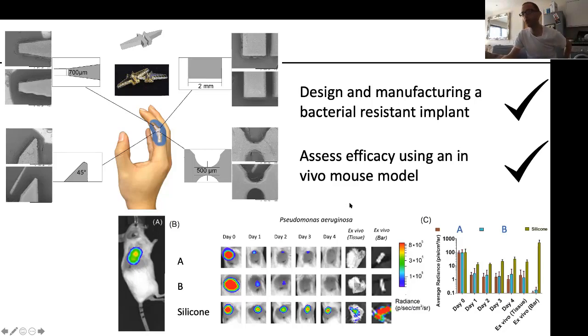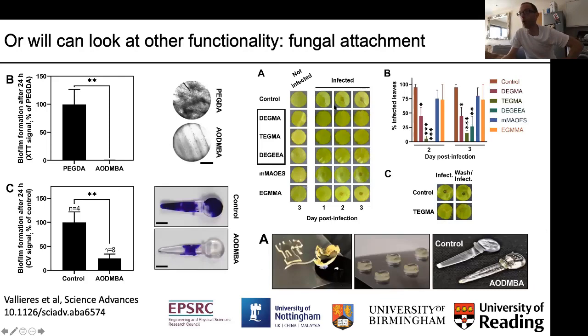It really shows a lot of promise for 3D printed formulations, but also it shows the promise of taking a screening approach to identify material properties. We also did this for antifungal materials, so we took a similar approach. In this case, just studying it in vitro, but again, in the bottom right, you can see 3D printed versions of materials that have been identified in a screening approach to resist fungal attachment, candida in this case. And when we tested our 3D printed constructs, the most interesting is the one on the bottom right, which is essentially a voice prosthetic, commonly again made out of silicone, really subject to prevalent fungal infection when it's placed in the body, and we showed that we can manufacture fungally resistant, personalizable 3D printed constructs. So that was really nice for us.